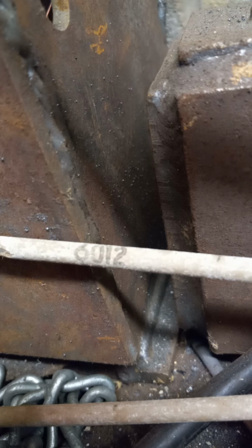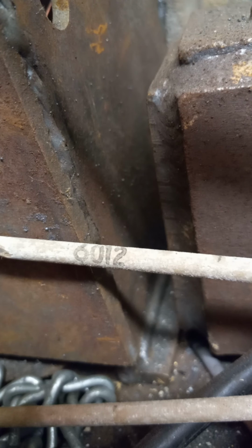The E6012 welding rod has a tensile strength of 60,000 pounds. It's an all-position rod with a flux of high titanium sodium. E6012 electrodes are characterized by a low penetrating arc and a dense slag that completely covers the bead. This may result in incomplete root penetration in fillet weld joints. The coverings are high in titania, usually exceeding 35% by weight, and they are usually referred to as titania or rutile type. The coverings generally also contain small amounts of cellulose and ferromanganese, along with various